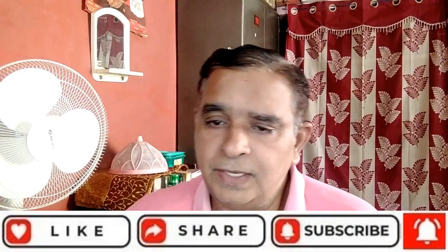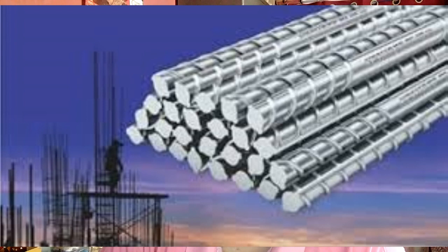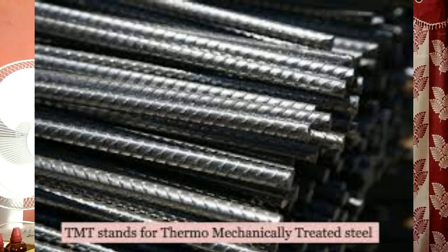austenitic at this stage. And the next, third and final stage, atmospheric cooling, takes place on the cooling bed. The final structure thus consists of a combination of a strong outer layer of tempered martensite and a ductile core of ferrite-pearlite. The rebar shall be produced in the range of 8 mm to 40 mm diameter.